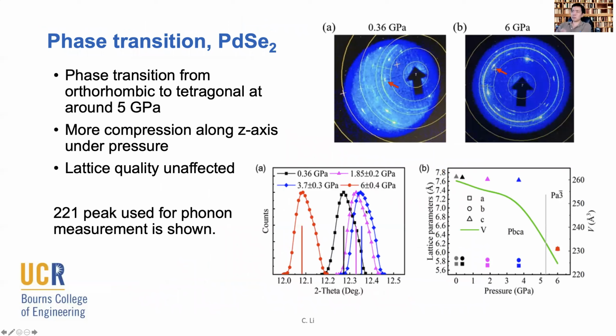So now we load the sample in the pressure cell, and as you can tell, we didn't go very high in pressure, simply because the van der Waals interactions are relatively weak, and to probe that we don't need any pressure above, in this case, 6 GPa. So we went as high as 6 GPa, and actually went across the phase transition around 5. This was previously characterized, so nothing new, but it's good to see that when we were doing inelastic x-ray scattering, we can more or less reproduce the lattice parameter that the prior measurement tells us. And we do see a phase transition between 4 and 6 GPa, which is in good agreement with the prior result.